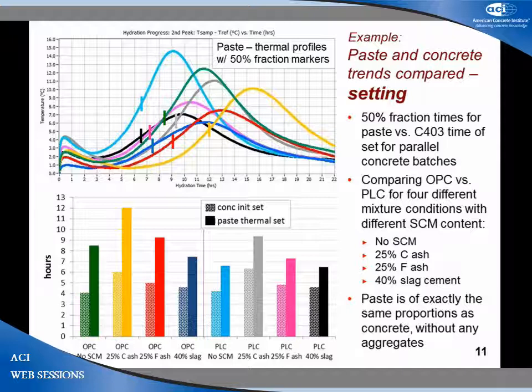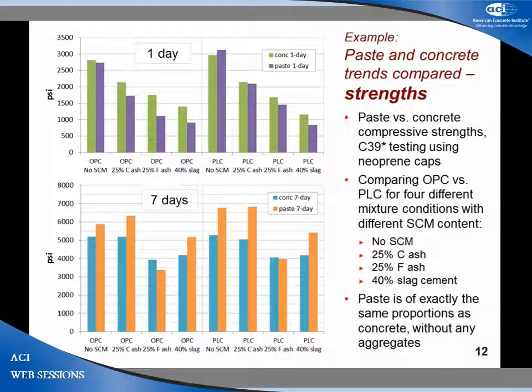Here's what the strengths look like. 1 day strengths here, 7 day strengths here, comparing the concrete 1 day strength versus the paste 1 day strength. The fact that these happen to be fairly close is really irrelevant for our purposes. That happens to be the case for this particular water cementitious ratio; it might not be for a different one. But the important thing is that the trends are quite the same.